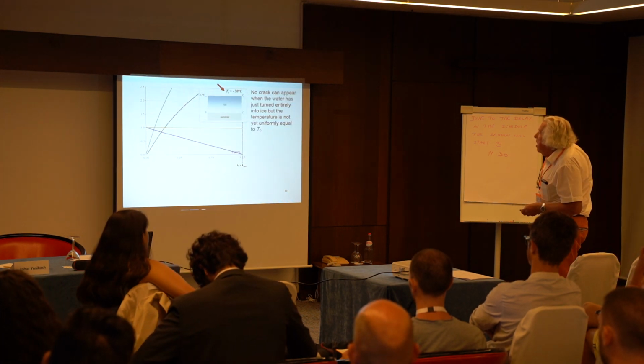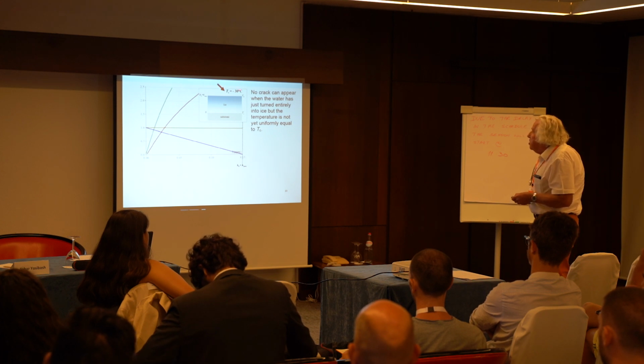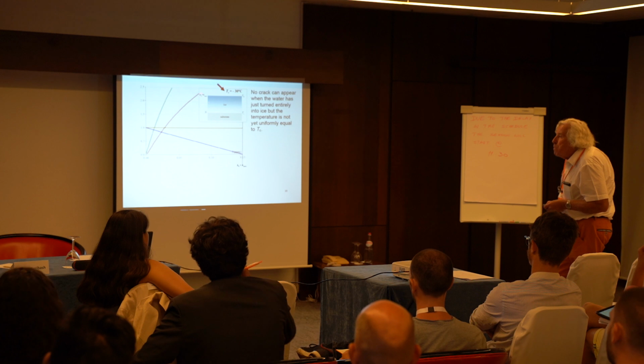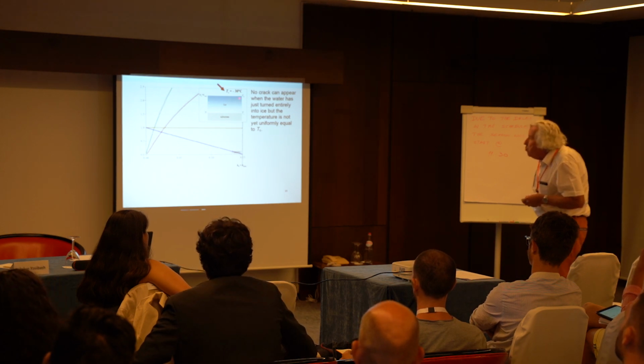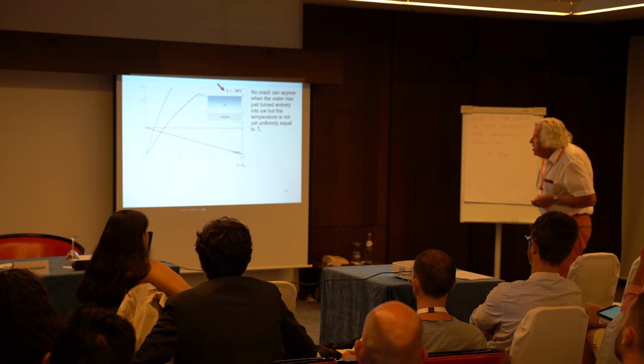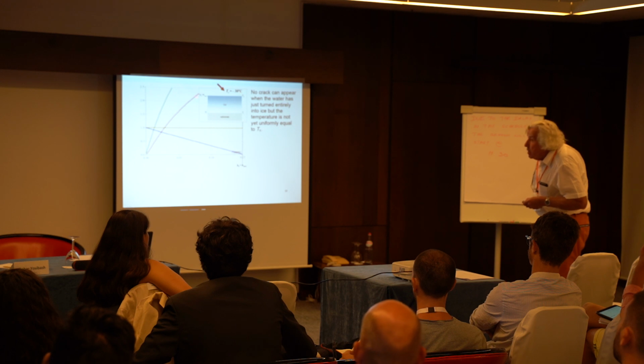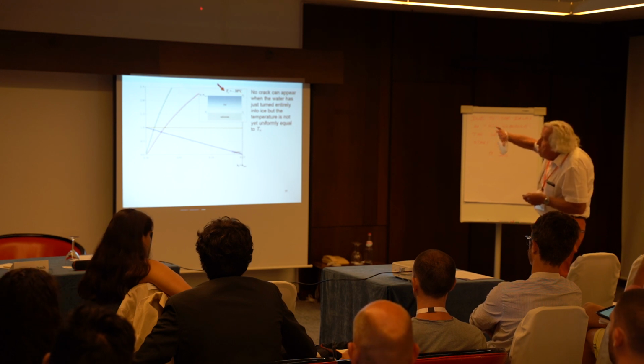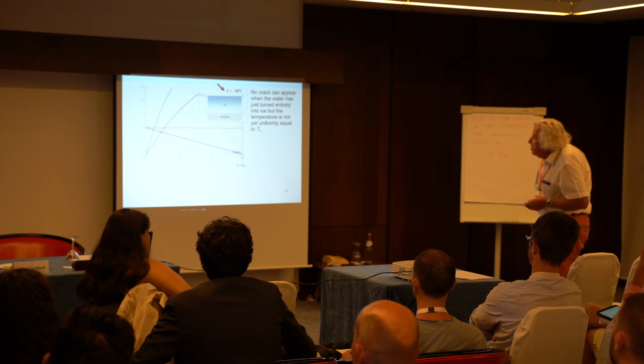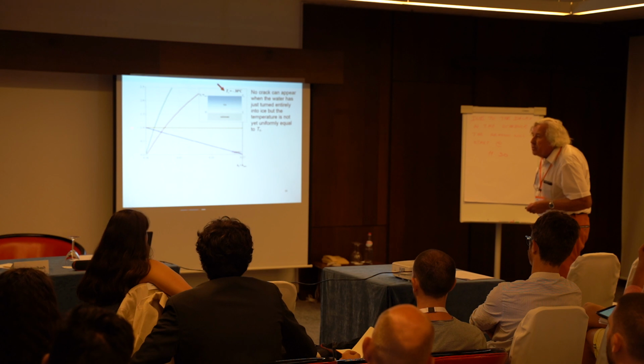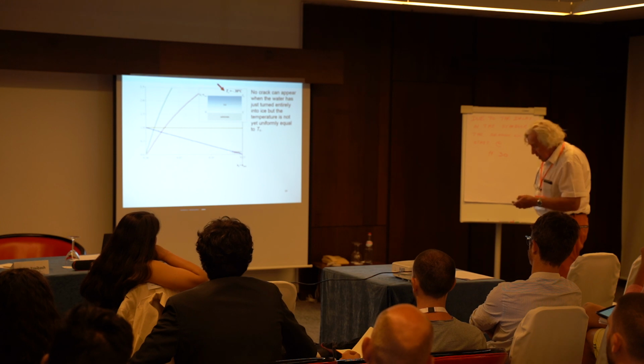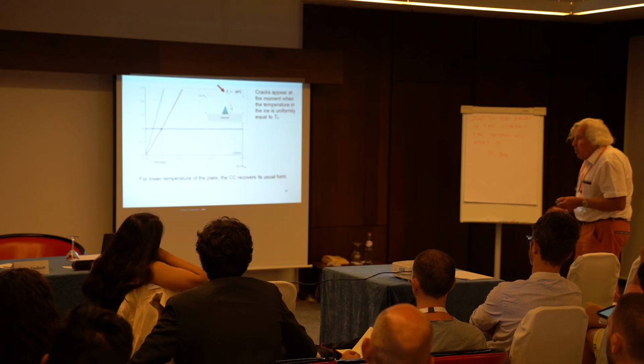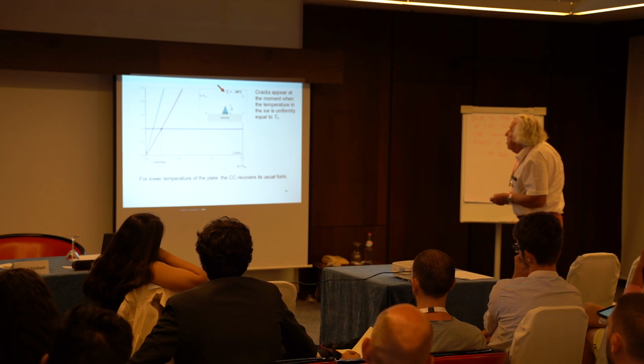So, nothing can occur. Let us now consider the temperature T equal to minus 30 degrees Celsius, but just when the water is just forming to turn into ice. It means that the temperature along the interface is minus 30 degrees, and here it is 0 degrees, because it is just the interface between water and ice that has finished. Okay? Then this means that the stress here is around 17, as we have selected, but here at the surface it is still 0. Okay?